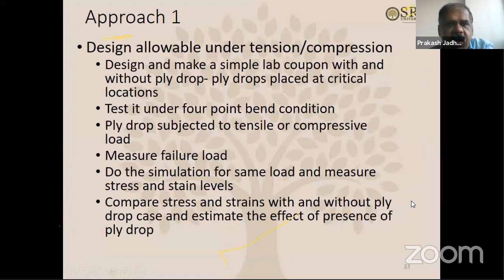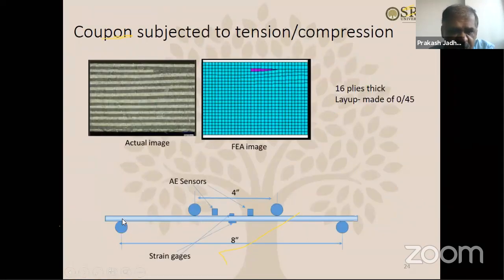So approach one: let's see how the coupons behave under tension and compression loading. We have decided to design and make a simple lab coupon with and without ply drop, with ply drops placed at the critical location. So how do you achieve tension and compression for the ply drop? I'll show you the picture here. We take a coupon like this, and we try to subject the coupon to the standard regular four-point bend boundary condition.